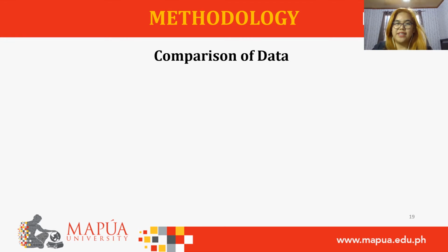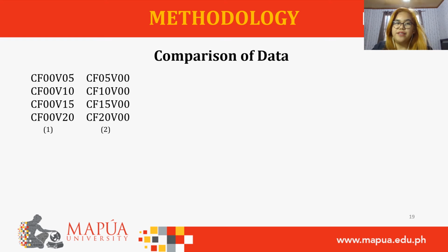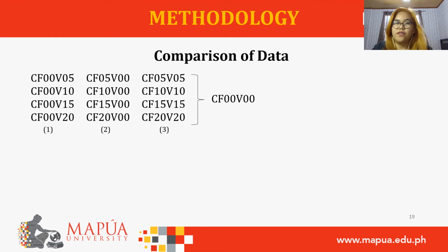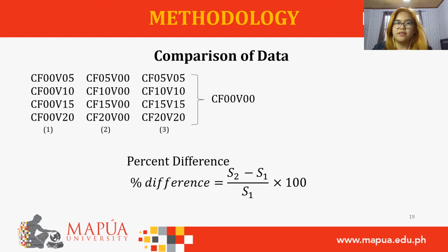Three cases were investigated, namely increasing volcanic ash composition, increasing face mask composition, and increasing both the volcanic ash and the face mask composition. The obtained data for each case was compared to the reference concrete CF00V00 by using percent difference. The libraries XCOM and EPDL97 were likewise investigated for their percent difference from the latest library, EPICS 2017.